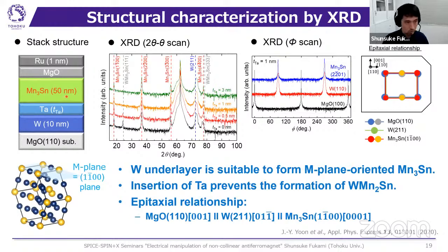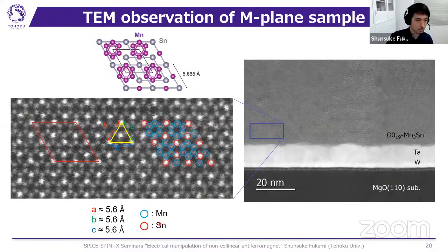So, as shown here, the D0_19 Mn3Sn has been successfully prepared. And this shows the phi scan results. From the phi scan results, the epitaxial relation was identified as shown here. So the MgO 110 direction and the MgO 001 direction... the Mn3Sn 0001 direction is formed in the parallel direction to the 001 axis of the MgO substrate.